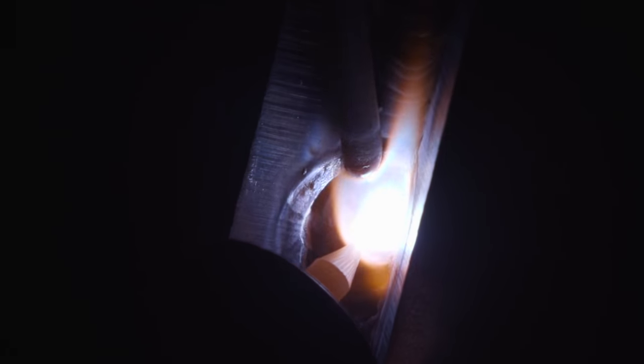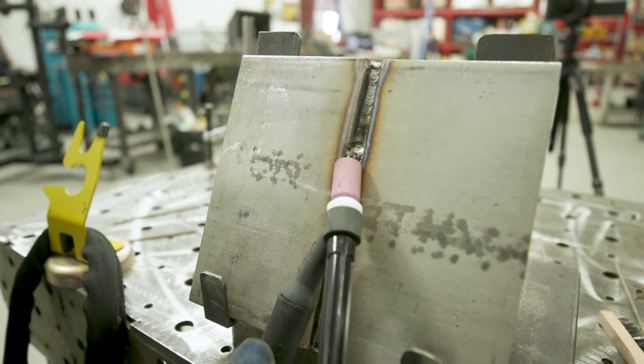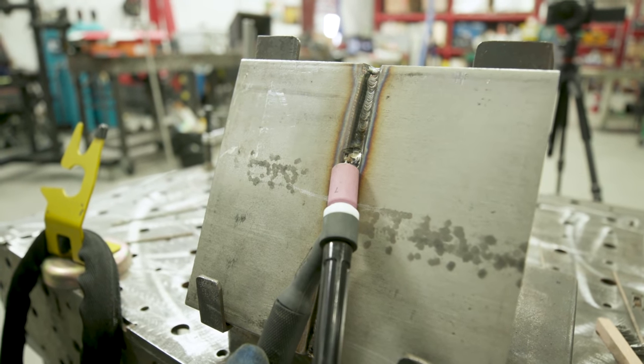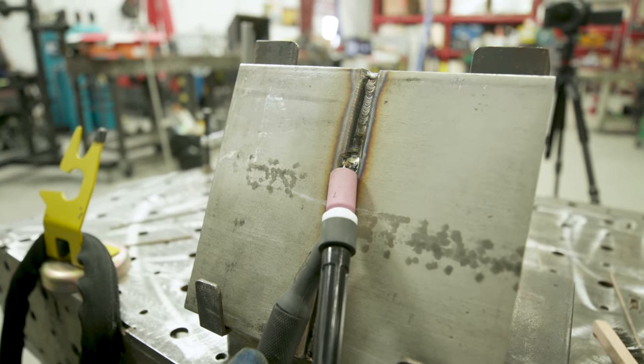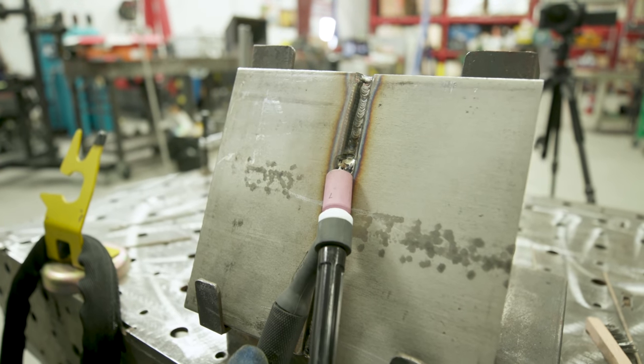Just letting it do the natural thing, like walking cup, same old technique. Just going back and forth. I'm using 3/32 filler, 1/8 inch E3 tungsten, the purple. I'm not even using full 120 amps, I'm using probably like 80-100. I'm not going to run this whole pass all the way up, probably like three quarters. I'm gonna come up on the bevel and pull off.